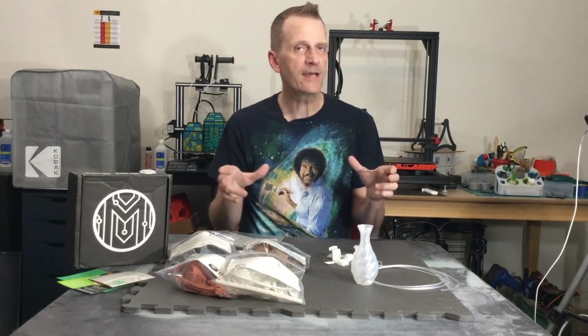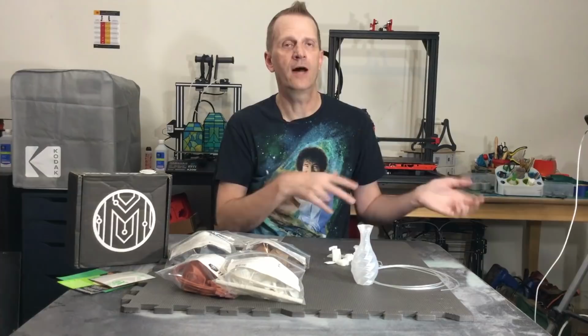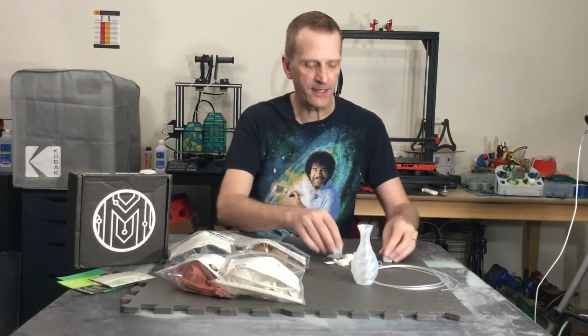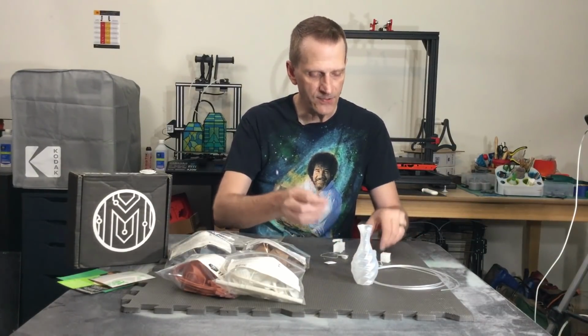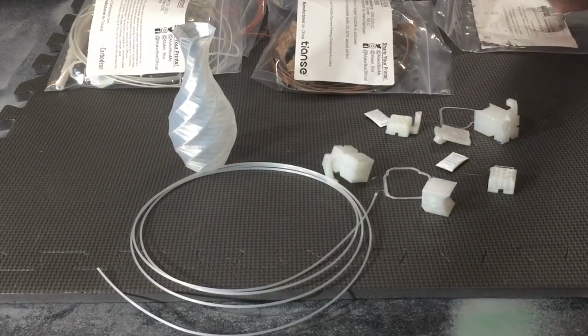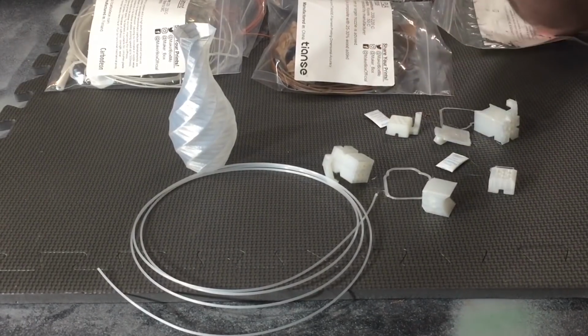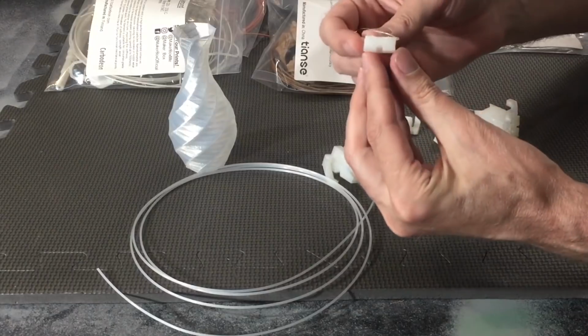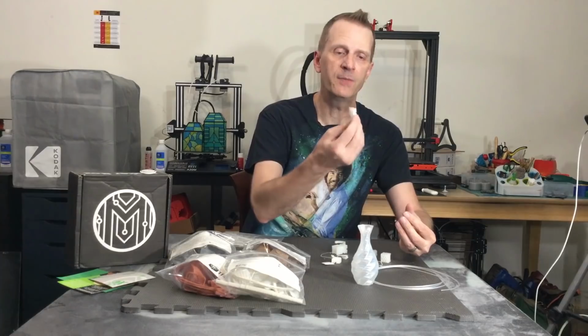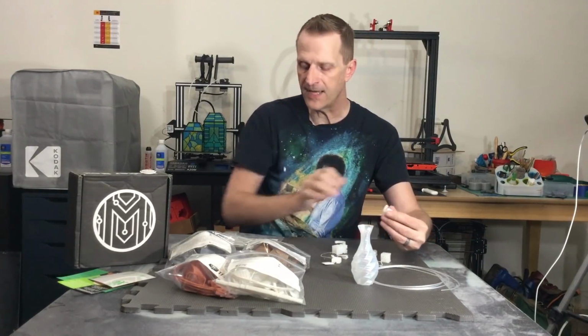So I removed the glass bed with the heated apparatus connected to it, and I put my acrylic on to print the first Cali Cat. So the first Cali Cat printed out, and that would be this one, on the sanded acrylic, because it says it doesn't need any special print surfaces. It printed out for a little while, and then it popped off the print bed because it was warping badly. And that is at